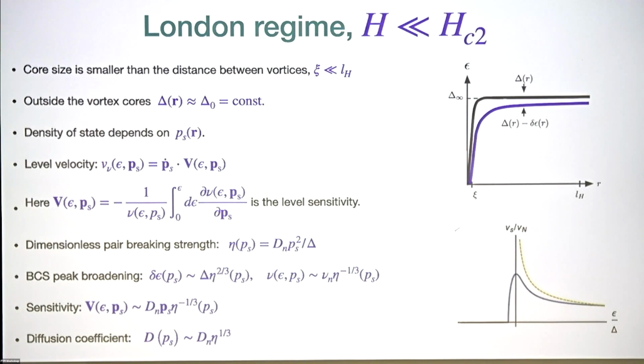Okay, so basically all life will happen outside the cores in this weakly inhomogeneous region. So in this region, in the London regime, the gap itself is uniform, and therefore the dependence of the density of states on time arises due to the condensate acceleration. And this is the sensitivity that Boris discussed earlier, which is a vector quantity. And so what's important is that all the properties that are relevant for the dissipation are occurring at the frequencies near the gap, near the broadening of the BCS peak. And the strength of pair breaking locally in space is described by this pair breaking parameter, diffusion coefficient times P_S squared divided by delta. It's small.